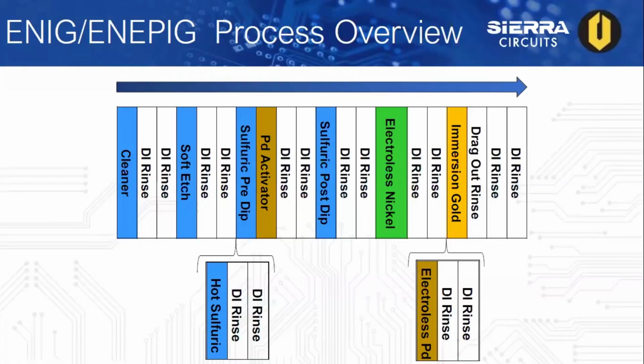Now, the sulfuric acid pre-dip is a common ion drag-in. And then next, you move on to a palladium-based activator, which will deposit a palladium seed layer of approximately 100 angstroms in thickness onto the panels. Now the sulfuric acid post-dip will then be used to remove any excess palladium, especially in the thicker panels that have those through holes.